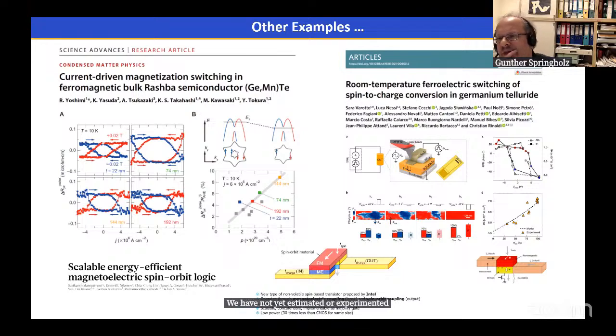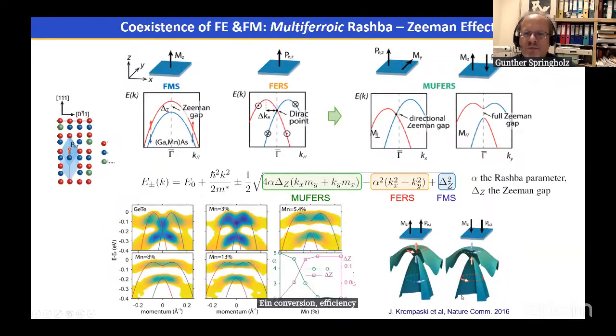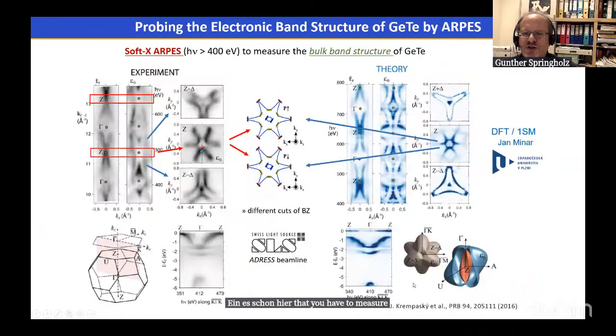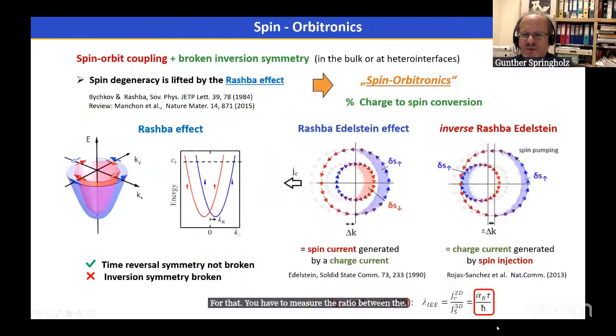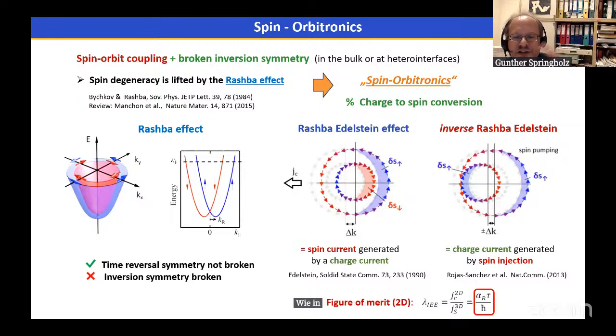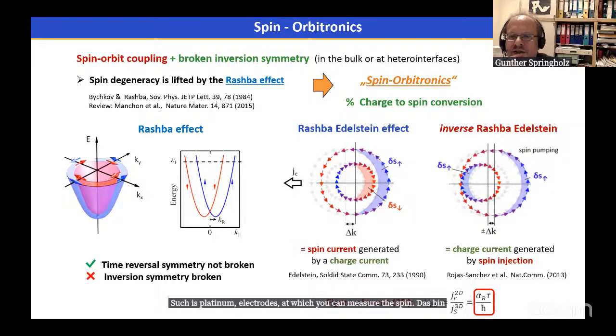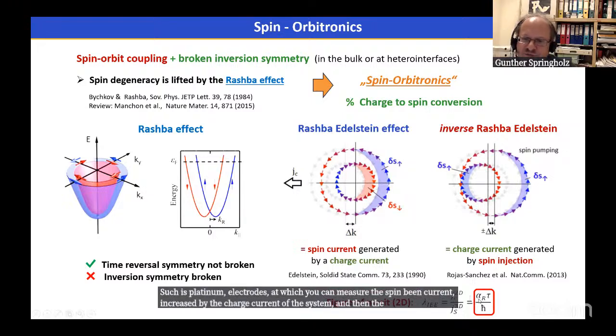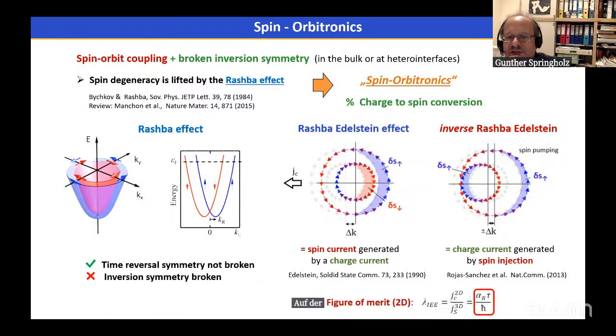estimated or experimentally measured the spin charge conversion, because we have to produce a device where we have a spin readout of the spin current and measure that relative to the charge current, because the conversion efficiency, as shown here on the slide, is the ratio between the charge and the spin current in the system. So we have to build a device where you have a charge current induced through the system, and then you need spin detectors such as platinum electrodes at which you can measure the spin current induced by the charge current of the system, and then the ratio is the figure of merit of the Rashba-Edelstein conversion coefficient.